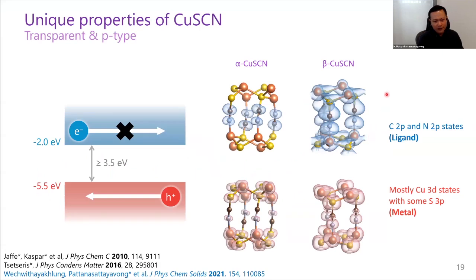So copper thiocyanate has a very unique feature. It's got a favorable valence band structure and also good energy levels that allow very good hole transport. And the conduction band is very high in terms of energy, so it effectively blocks the electron. So it's been used a lot in organic solar cells, perovskite solar cells, as well as light emitting layers, and also in photodetectors and so on. It's transparent, inorganic, and solution processable.